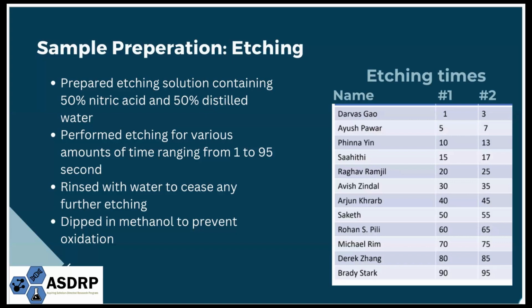So our next step is the etching. To visualize grain boundaries, we have to use a certain combination of acids to etch the sample. In our case, we use diluted nitric acid, in a 50:50 ratio. This art of sample preparation is a little bit tricky, so it takes quite a bit of iterations, maybe a couple of steps forward and one backward.